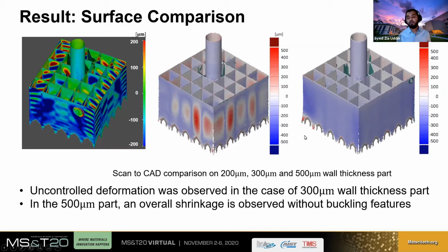And in the 500 micron wall thickness part, we see there is an overall shrinkage of the part indicated by the bluish color, but there is no large out of plane deformation, which is very encouraging. But we have to remember that our requirement for this particular application is to be able to print 300 micron wall thickness parts. So we still got some work to do there.